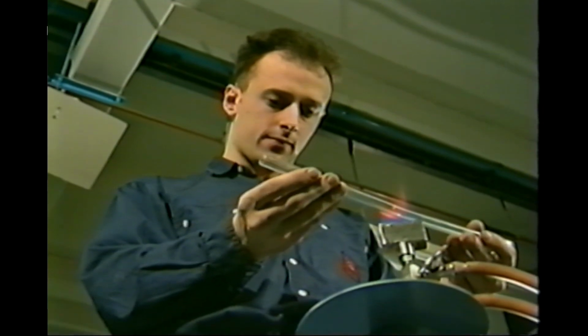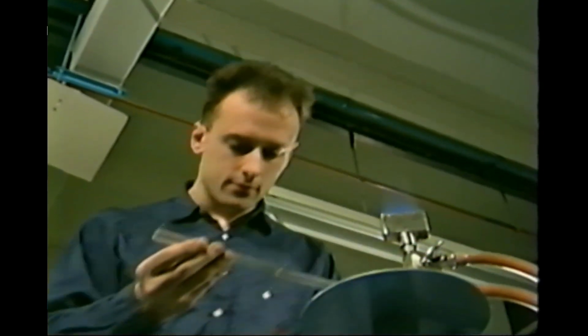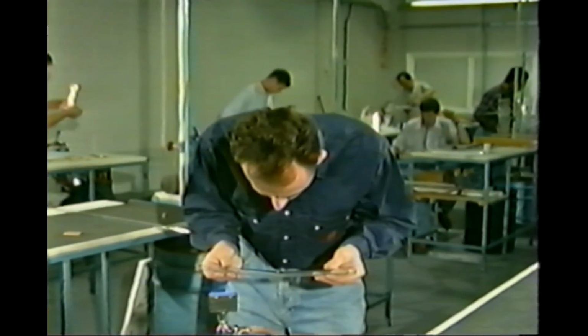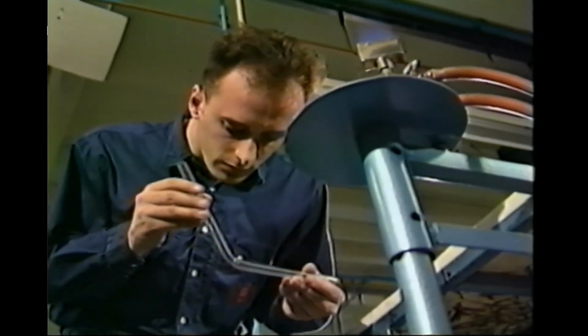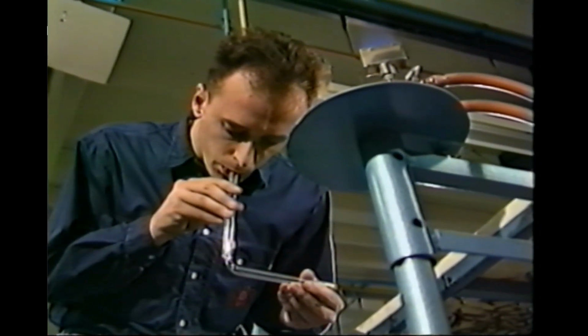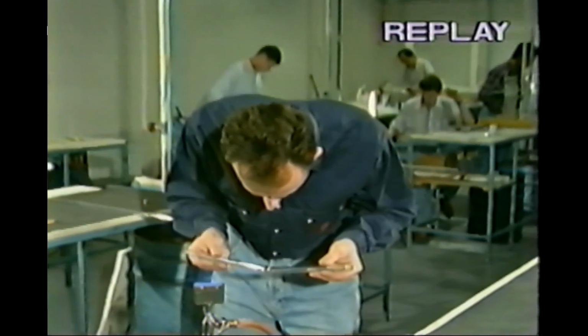After melting the bottom area opposite the mark, bring the tube out of the flame to waist height, keeping the tube horizontal. Lean forward and down from the waist and keeping the side arm in the left hand horizontal and the mark directly below the head shape, the side arm in the right hand in this sequence: out, round and up in one easy flowing motion. The correct radius can only be achieved using this movement.